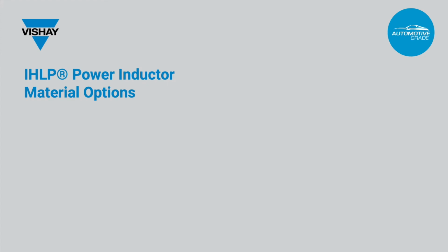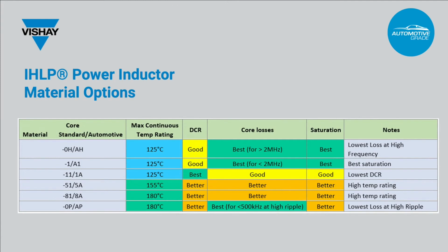One more benefit of the IHLP family of inductors is the material options that are available. When this technology was first created and released for production, there were only two material choices available, both topping out at 125 C with regard to the maximum continuous operating temperature. The -0H/AH material was optimized for very high frequency operation, up to at least 2 MHz, so it exhibits the best saturation performance and lowest AC core losses possible. The -11/1A material, on the other hand, was optimized for the lowest possible DC resistance. It still has good frequency characteristics, up to at least 2 MHz, and the AC core losses and saturation performance